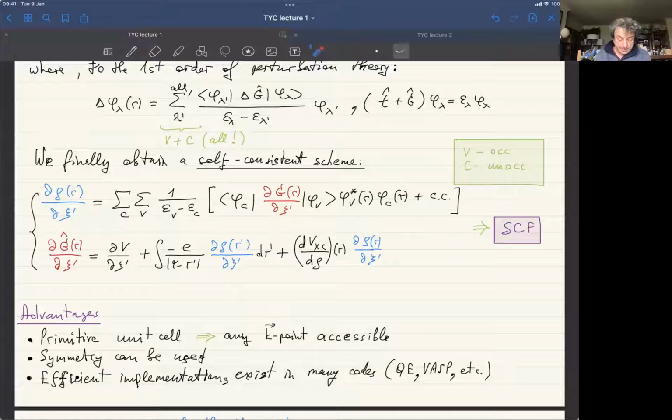Yeah, and that procedure doesn't require having cells of extended size. The calculation can be performed just on a primitive cell, and you can do the calculation for any K point. You just need to generate a special normal coordinate which would excite a phonon of a particular K vector. Yeah, and that would be our Xi.